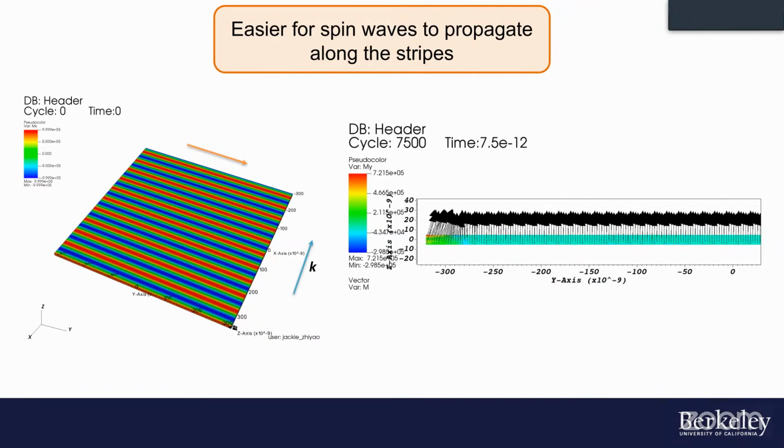This amplitude is scaled up just so we can see it, but we have Ising-like spins that are precessing in the way we would expect it to. And so by then engineering the direction of the cycloid, we can potentially tune the magnon transport in this material, which is something that we're very excited about, because again, the structure can also then be switched with an electric field.